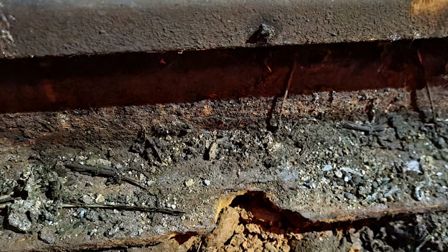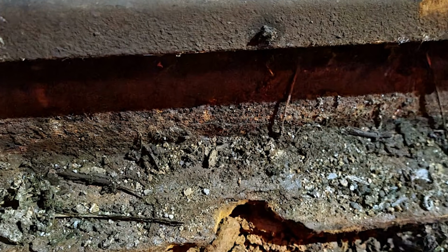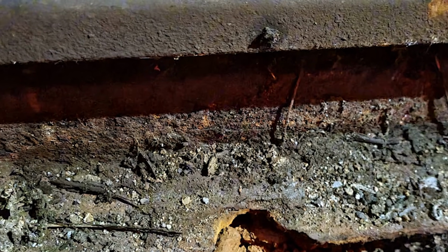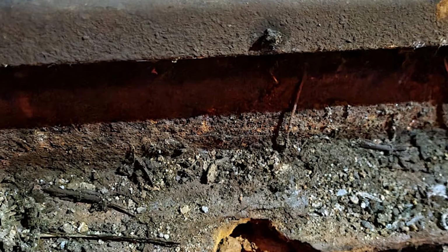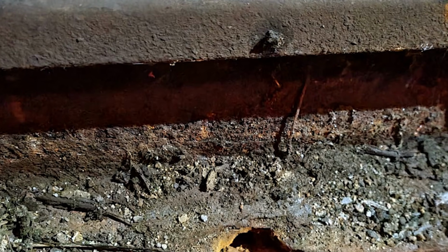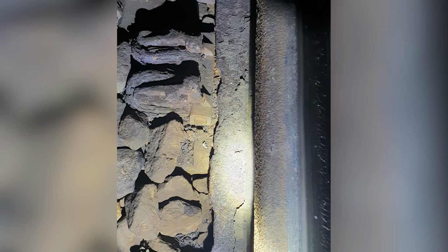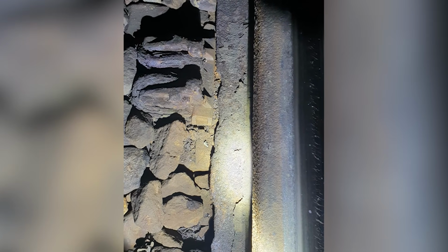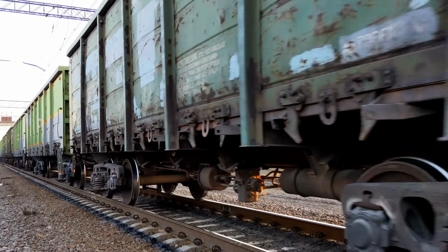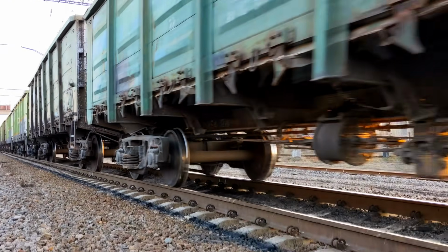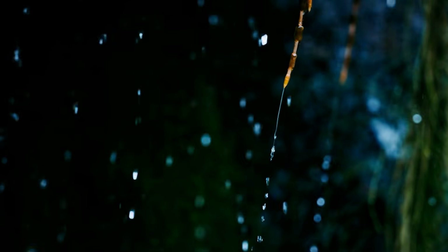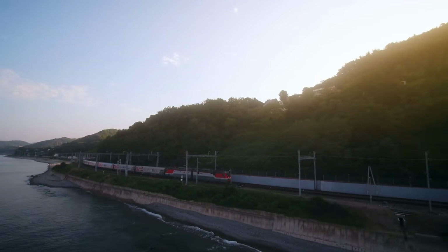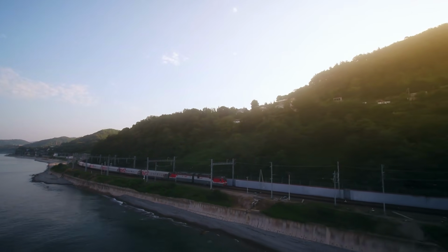The rail foot, as the area closest to the ground, is often the part of the rail most affected by corrosion. This area of the rail is important to the overall rail's strength as it contributes to the rail's bending strength. It can also be harder to inspect visually underneath the rail foot, leading to corrosion progressing before being spotted. So where is corrosion most likely to occur? The quick answer is areas that are wet. This could be inside tunnels or areas with poor drainage. Another factor can be salt, such as coastal routes.